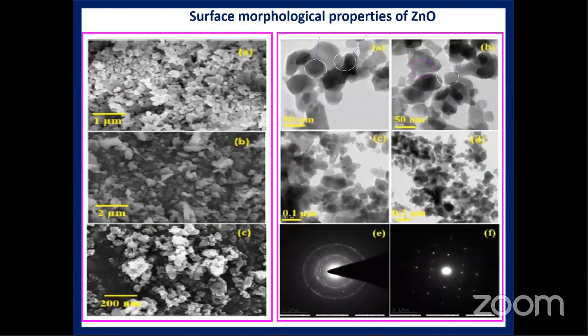You can see the surface morphology of the zinc oxide nanostructure at different magnifications of the same image. You can see that spherical shaped grains are located and highly agglomerated. We can also confirm with the transmission electron microscope that the grains are spherical in shape, and from this we can calculate the particle size. The SAED pattern also confirms very good agreement with these planes. You can see the concentric circles indicate each plane of this structure.